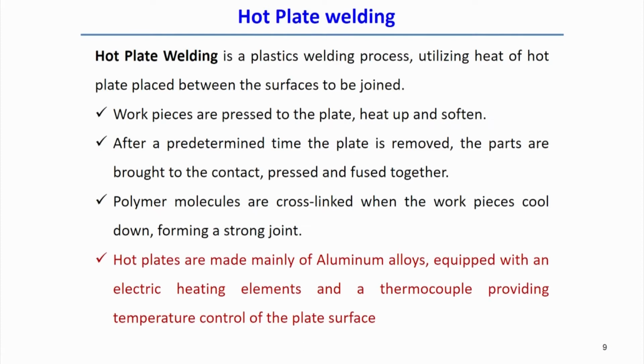Now, next we will discuss hot plate welding. In hot plate welding, instead of continuous hot air, we use a hot plate to heat the plastic components, and these hot plates are placed between the surfaces to be joined. The workpieces are placed against the plate and gradually heated, and then finally the plastic component softens. After a predetermined time of heating, the plate is removed. After that the parts are brought in contact, pressed, and finally fused together. So, polymeric molecules with the same principle cross link when the workpiece cools down, and finally it forms the weld joint.